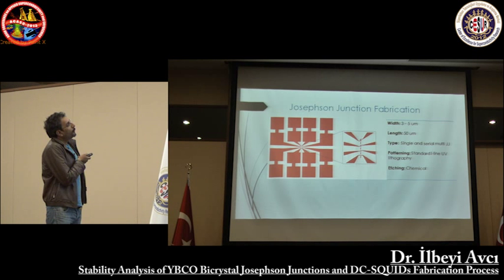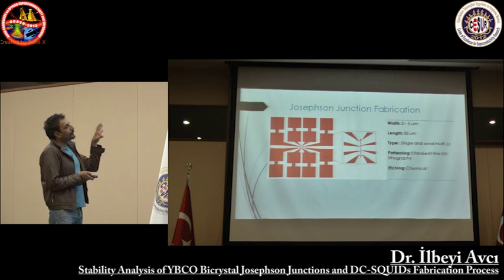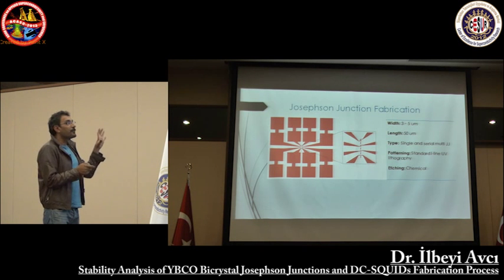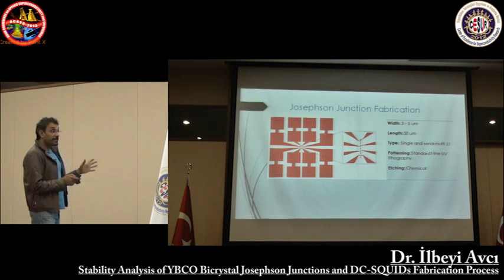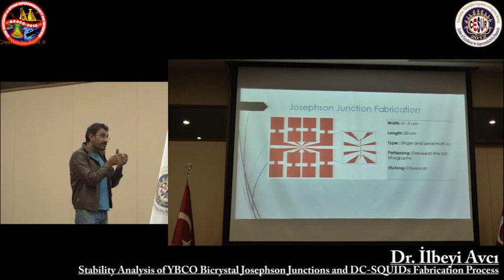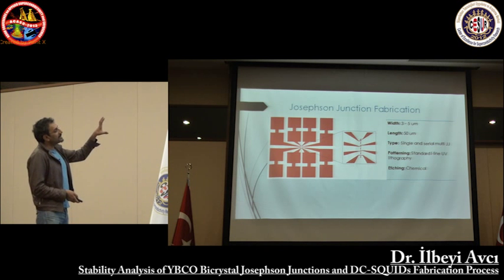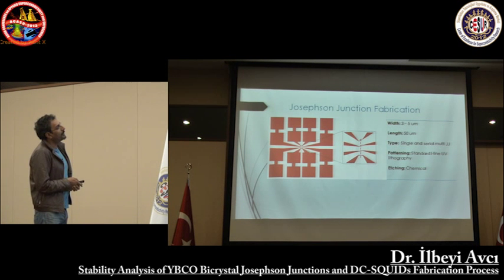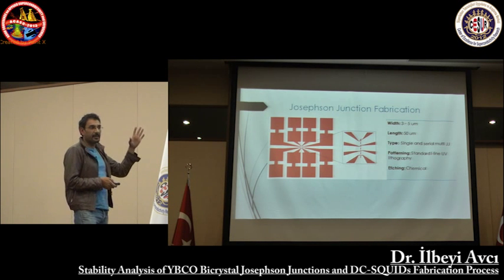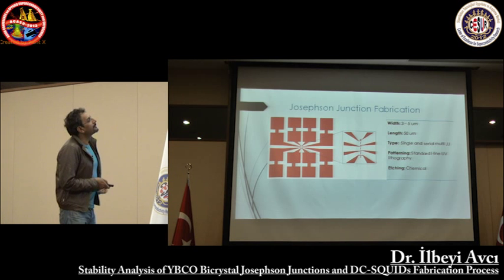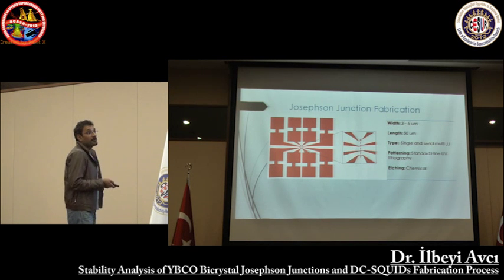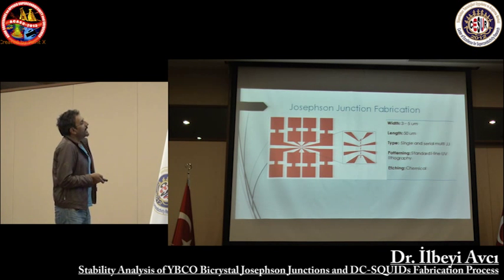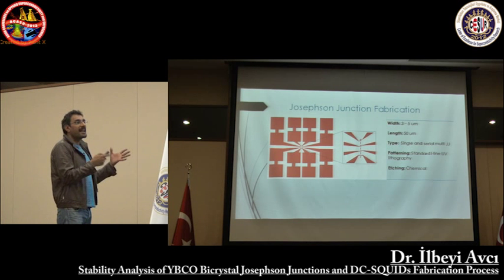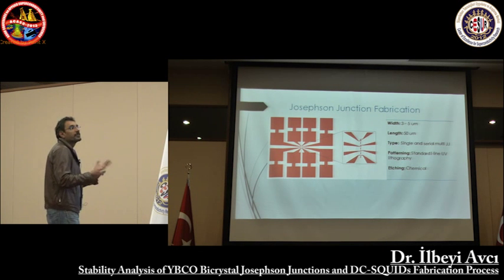For the optimization of the Josephson junction, first of all, we have to design the type of the Josephson junction. The width of the junction is a very important parameter, and the strip line is another important parameter. This is the latest Josephson junction designed with YBCO. We are using 3, 4, and 5 micrometer width junctions with a 50 micrometer strip line. We use one single junction in order to get the critical current values of the single junction,